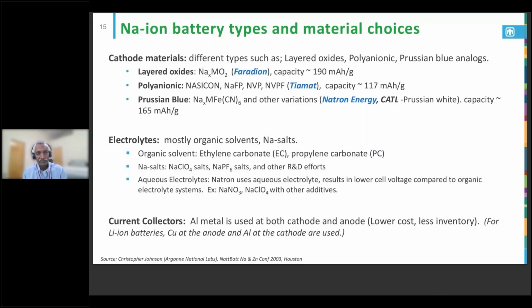Electrolytes, most of them are using organic solvents with sodium salts. Very typical as in lithium-ion batteries, ethylene carbonate and propylene carbonate. Only the difference is in the salts. Instead of lithium salts, they use sodium salt, like sodium perchlorate or sodium hexafluorophosphate. Only Natron is using aqueous electrolyte. It has advantages, but it has a lower cell voltage with the aqueous electrolytes. So the energy density is slightly lower, but it's safe compared to organic electrolytes.